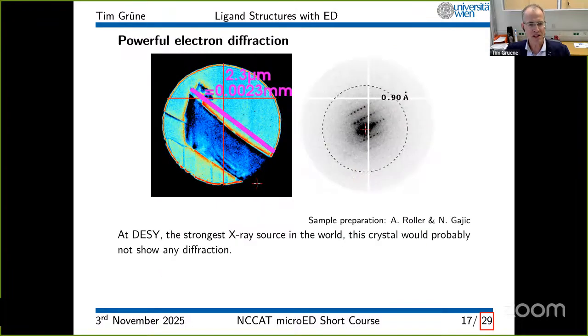And we took them into the electron microscope, and we found these needles on the TEM grid. And this is only 2.3 micrometers long here, and the width is even less than a micrometer. Yet this crystal diffracted to 0.9 angstrom, which for chemists is great. This is about the limit that you want to have for publishing a chemical structure. Of course, for proteins it's different, but it's just at a different scale. With a protein crystal, you get 1, 2, or 3 angstrom resolution. But again, electrons are so strong that they get the best out of your crystals.